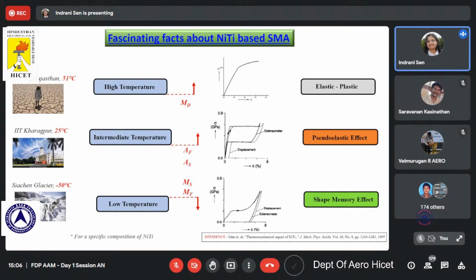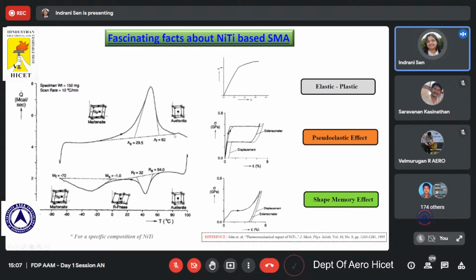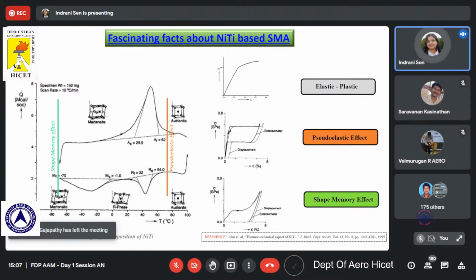So this material at high temperature behaves like a regular material, like any other metallic system, an elastic plastic one. Whereas at intermediate temperature, it has a pseudoelastic effect, and at low temperature, it shows the shape memory effect. All of this occurs because of the phase transformation that this material undergoes as the temperature is changed. So even if we are not applying any stress, just by changing the temperature, the phases change, and that leads to all different kinds of properties and characteristics for this alloy. At comparatively high temperature we see the pseudoelastic effect, whereas at comparatively low temperature the shape memory effect is active.